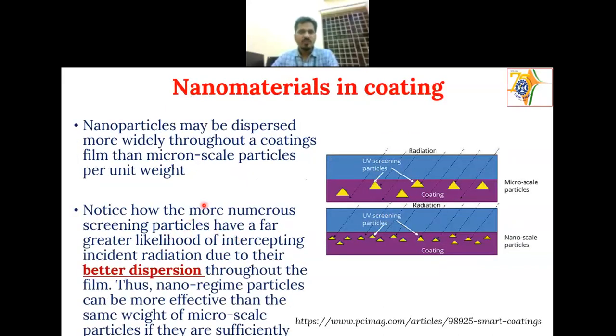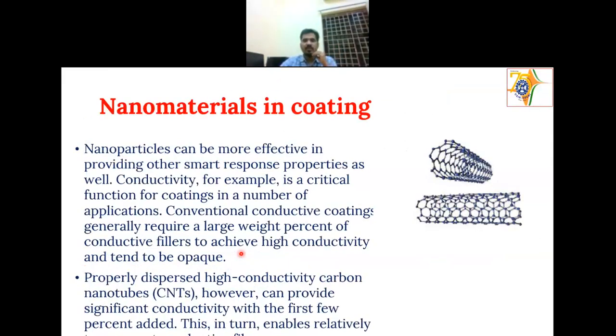And then you see, if I use nanomaterials in a coating, how is it better? In the image, you can see the first one uses a micro scale particle, the second one a nanoscale particle. You can notice that if you finely disperse these nanoparticles in the coating, and better dispersion is very, very important throughout the film, this particle can be more effective than the same weight of micro scale particles. And then the carbon nanotube improves the conductivity of the coating.